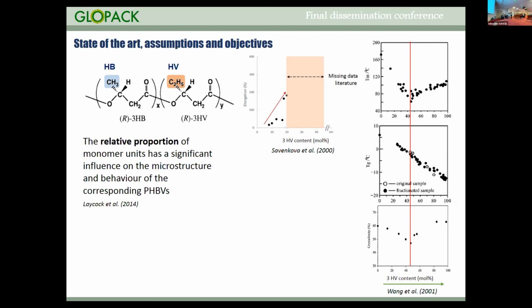So they are copolymers, but they are also semi-crystalline. That means that in the polymer you have the coexistence of an amorphous phase, which corresponds to very disorganized polymer chains, and also a crystalline phase, which corresponds to chains which are very well organized in crystallites. Here you have some interesting results given in the literature.